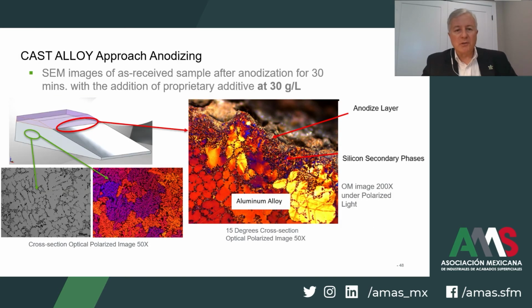Shown here, some special cross-sectioning techniques were developed, including defining the angle of surface sectioning and using some polarized imaging to see the different alloy elements and also the pore structure, considering their shape, their size, and their orientation in the alloy. Being able to see microscopically what was going on was very critical for us in a roadmap for the development of the chemistry in the sulfuric acid anodizing electrolyte.